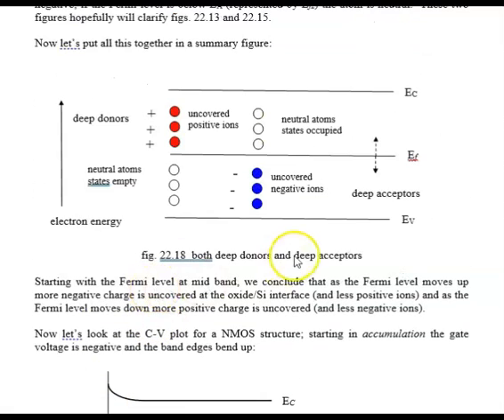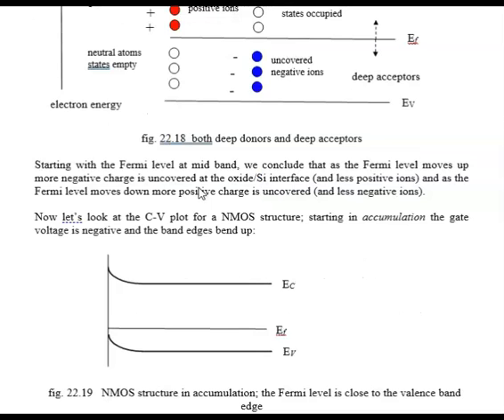So the Fermi level has gone down, and if the Fermi level goes down, what happens? Well, we can see that from figure 2218. Fermi level goes down. I have less of these guys. This guy, for example, will become a neutral unfilled circle, but this guy will become a red-filled positive circle. So I have a positive Q at the interface. That's exactly what we had when the mobile charge distribution was at the interface. The mobile charge distribution was positive. When it's at the interface, it has a maximum effect.